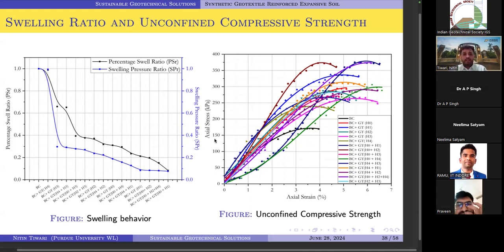We also did the unconfined compressive strength, and you can really observe that initially we had just around 130, 140 kPa of UCS value, and it went up to more than 350 kPa. So these results show that not only the soiling behavior, even the strength behavior can be controlled with this kind of treatment.